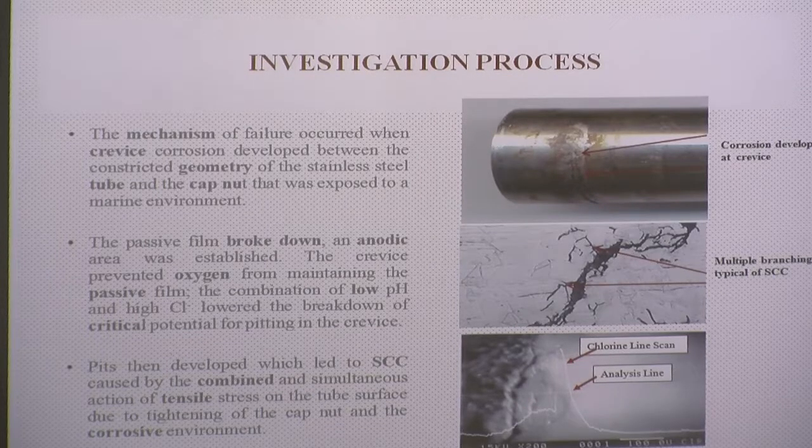So what happened here? Because of the constricted geometry between the cap and the pipe, you had crevice corrosion taking place. The passive layer broke down, and then you have this chlorine element from the sea. It attacked the material. And you had this combined action of stainless steel being a susceptible material, the chlorine environment, and the tensile stress, because when you tighten the cap, that forms the stress that caused the stress corrosion cracking.